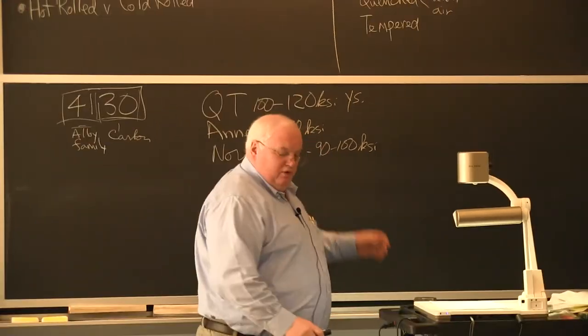If I'm adding molybdenum, this is zero molybdenum. I may have shown you this the other day: 0.15, 0.3, 0.38, and 0.5 molybdenum. You can see the nose of the C-curve getting pushed over from about 2 seconds all the way over to 20 seconds. I can slow down the reaction by a factor of 10 by adding 0.5% molybdenum. So that's what I've done with 4130. I can't remember, I think it's chrome that they added to the 4130 to slow down the transformation so I can get all these wonderful phases that I would like, as a metallurgist. So I can buy the tubing in a number of different forms.